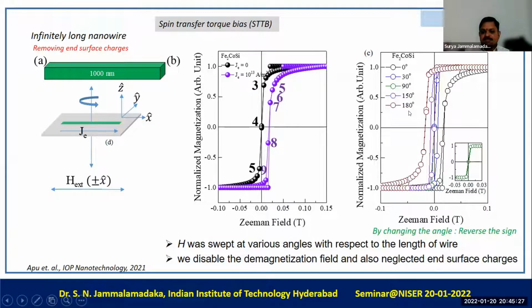Now, as I mentioned, we tried to change the angle: 0 degrees, 30 degrees, 90 degrees, 150 and 180 degrees. At 0 degrees, we do see the shift of the magnetization loop on the positive field axis. And for 180 degrees, we do see a shift of this hysteresis loop along the negative field axis. So the advantage of the spin transfer torque bias is that you don't have to have an antiferromagnetic layer. But just by changing the angle between the magnetic field and the length of the wire, you can actually tune the exchange bias values from a positive value to a negative value. But of course, if someone can prove this experimentally, it will be miraculous in the spintronics area. Whatever I'm showing here is basically on a simulation basis.